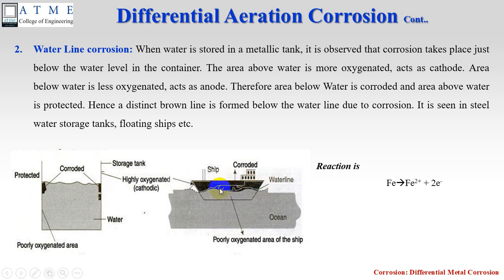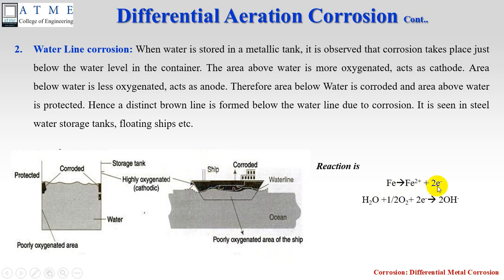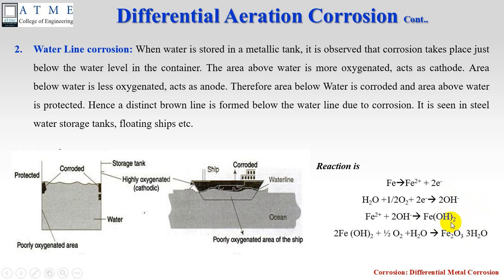Another example is a ship, which is always placed in water. The ship's metallic surface is exposed to two different oxygen concentrations — one inside the water and one outside. The part inside the water becomes the anode, and the part outside becomes the cathode. The anodic reaction is Fe → Fe²⁺ + 2e⁻ (oxidation). The cathodic reaction is H₂O + ½O₂ + 2e⁻ → 2OH⁻. Then Fe²⁺ reacts with 2OH⁻ to give Fe(OH)₂, and further oxidation gives Fe₂O₃·3H₂O. The corrosion product forms just below the water line — hence it is called water line corrosion.